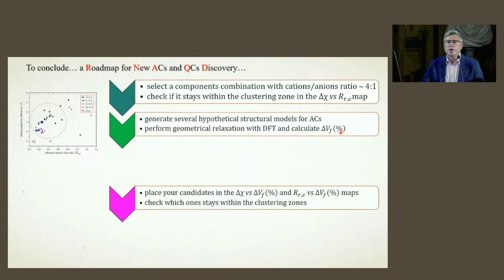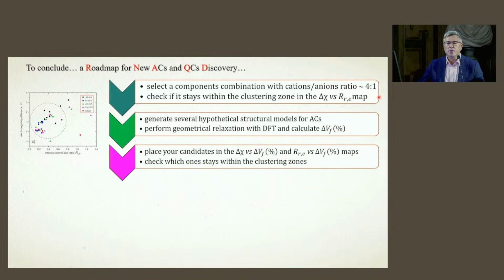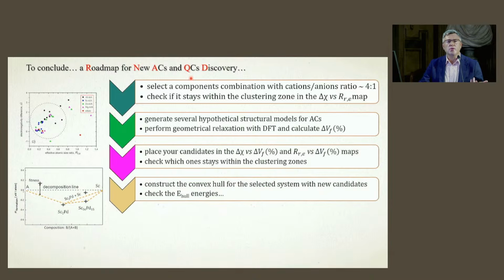In this way you can put two more plots and verify whether they fit within this circle all the time. If yes, why not construct a convex hull and see where the energy of your approximant will be with respect to the convex hull curve.